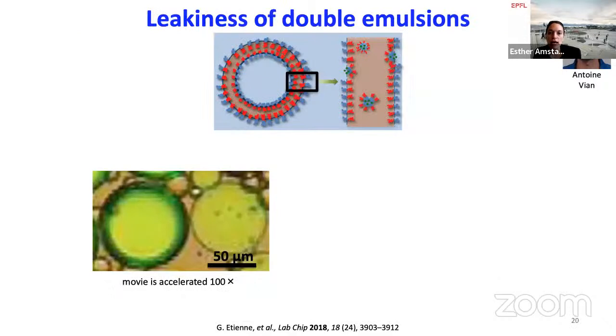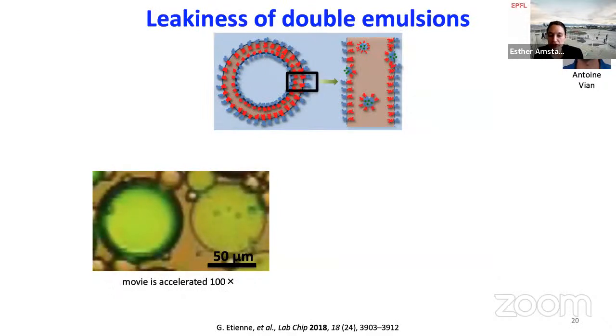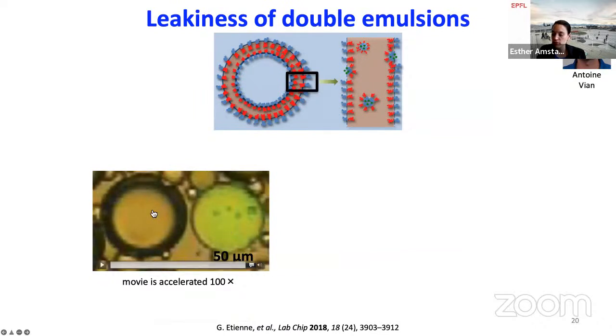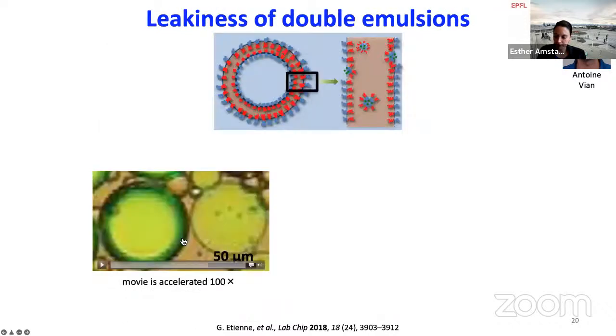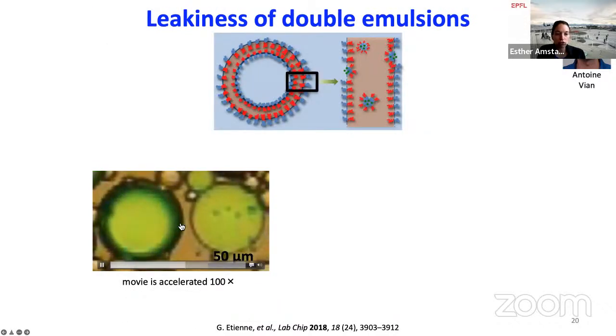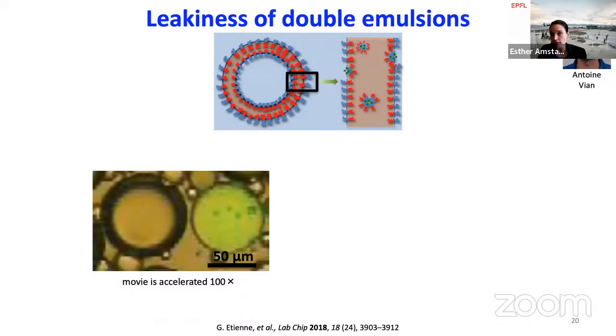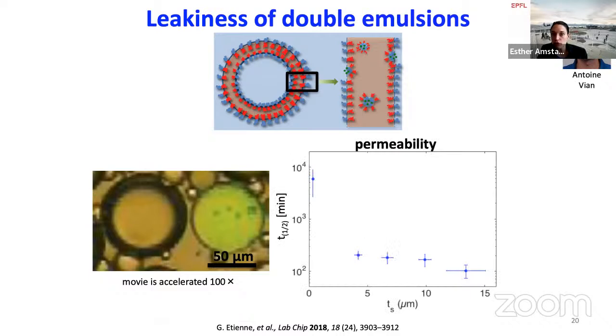Now, by doing that, we could indeed reduce the permeability of the shell towards the fluorophore, as you can see here in this movie. I'll play it again. Sorry. Here you have a double emulsion with a shell thickness of around 10 micron, and this is 300 nanometers, and you see that the one with the thinner shell leaks significantly slower. And that is counterintuitive if you just think about the diffusion. But if you think about the formation of these small drops, it becomes more intuitive.